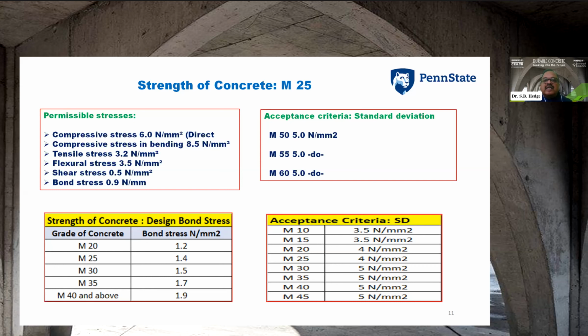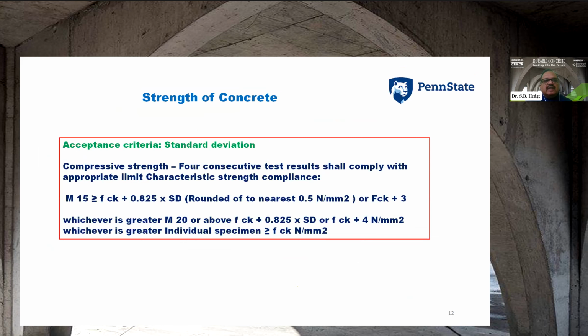And the acceptance criteria, if you see, the standard deviation for M50 is 5 N/mm², M55 is 5 N/mm², and M60 is 5. And the acceptance criteria as I have shown from M10 to M35. This is the acceptance criteria of standard deviation of the strength of the concrete. You can see from the slide.